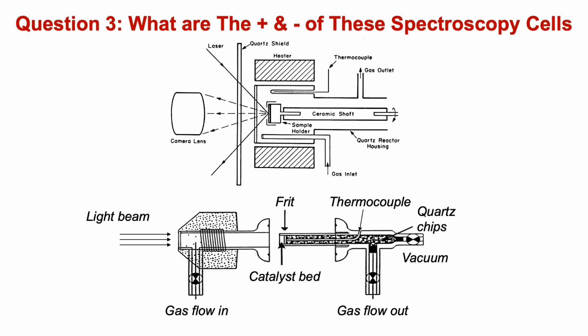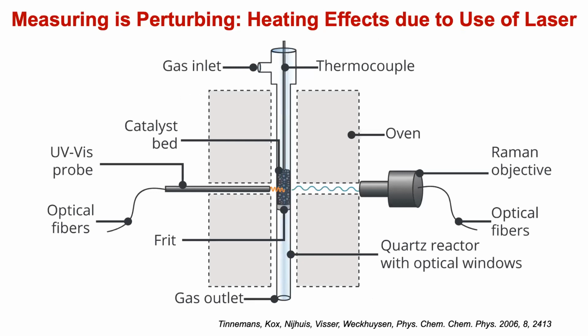In the top one, actually, the thermocouple does not tell a lot. I think we should be careful on that. Now, I hinted at heating effects, and I want to show you a reactor which we have been developing. On the left is UV-vis, on the right you see a Raman objective. This is a system where you measure UV-vis and Raman, not on the same spot, but on a bit of the same catalyst.